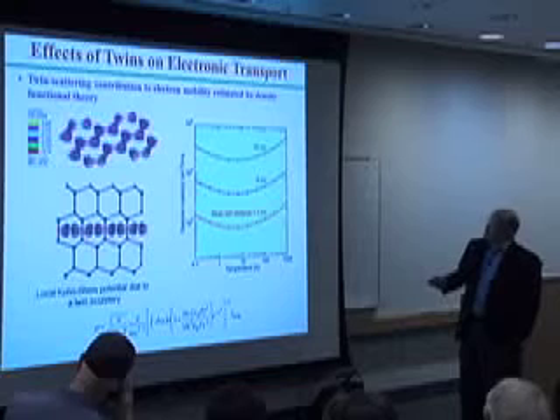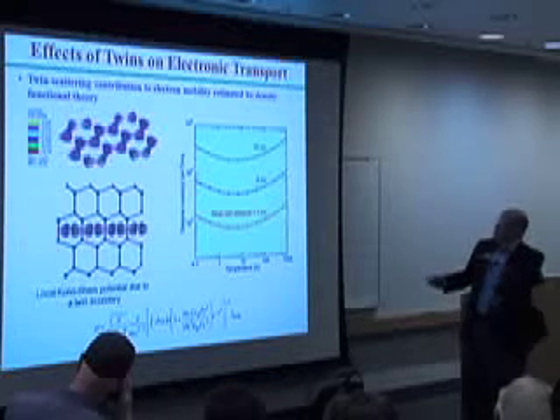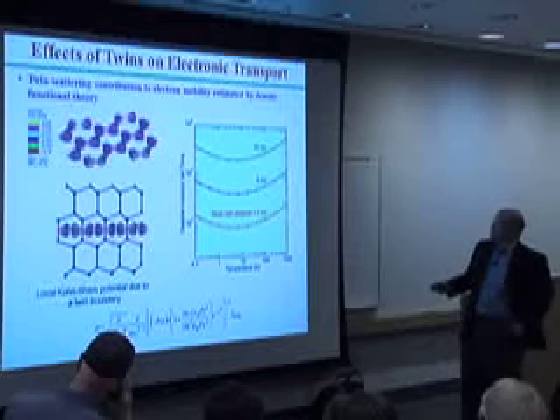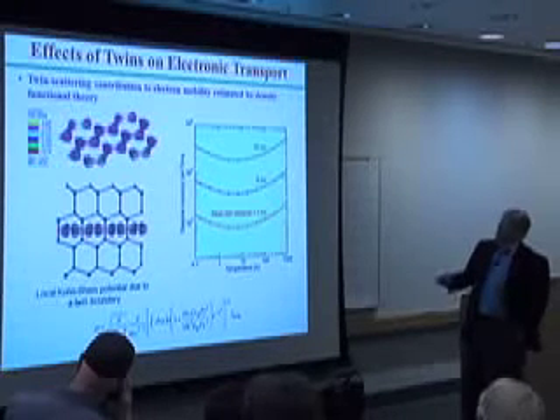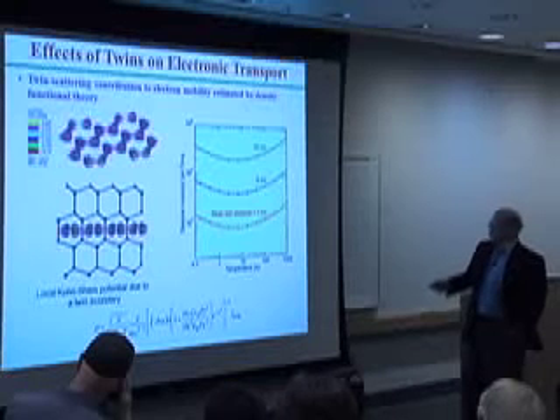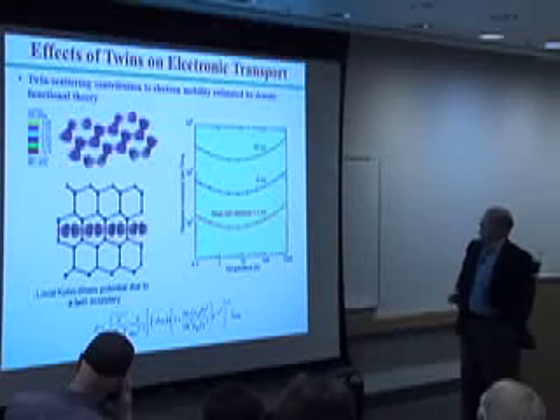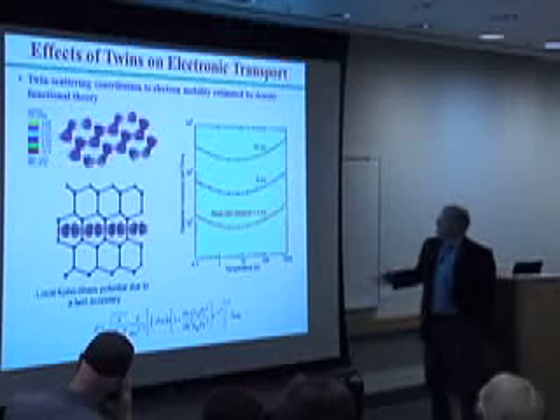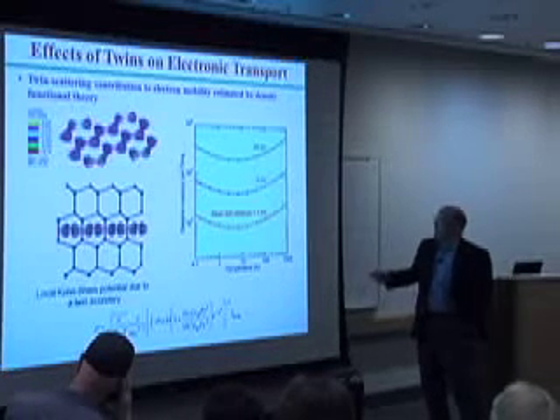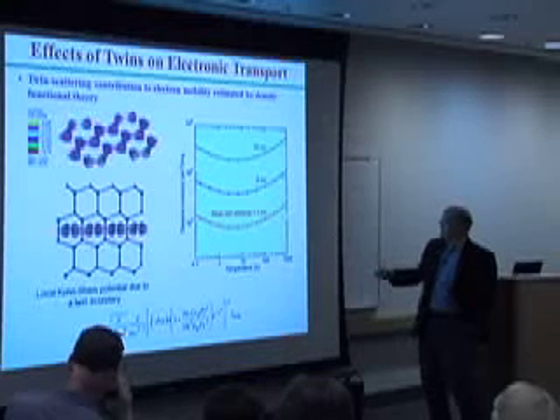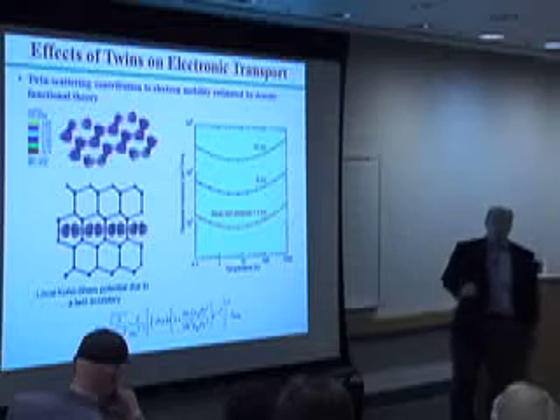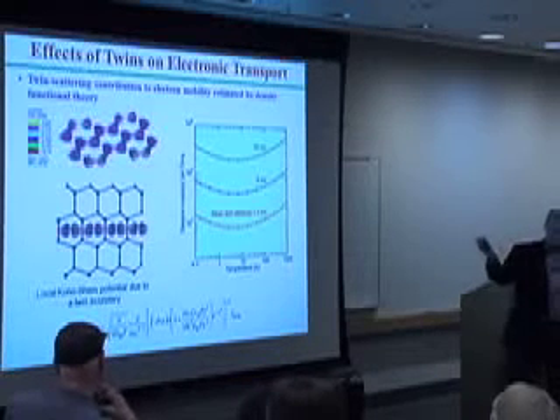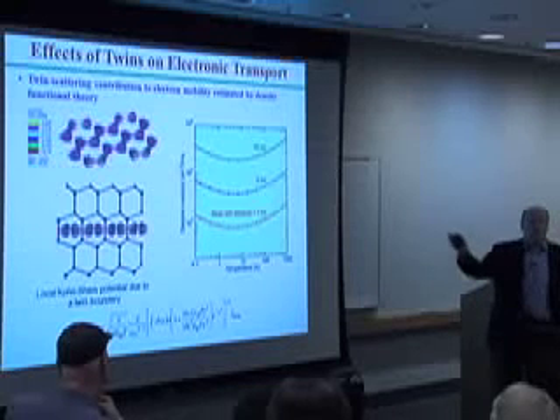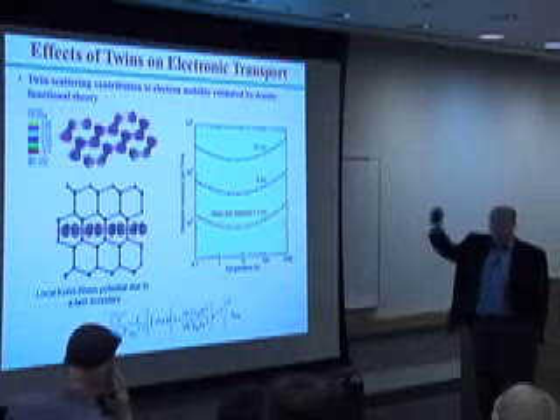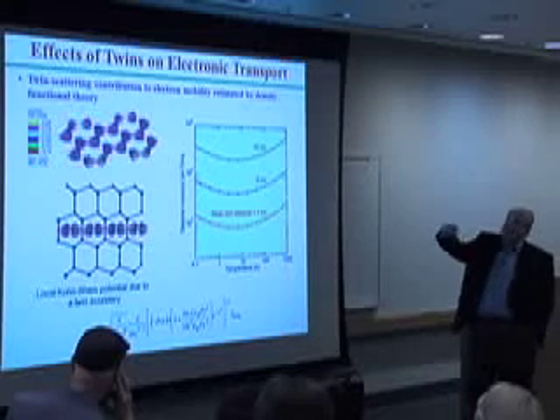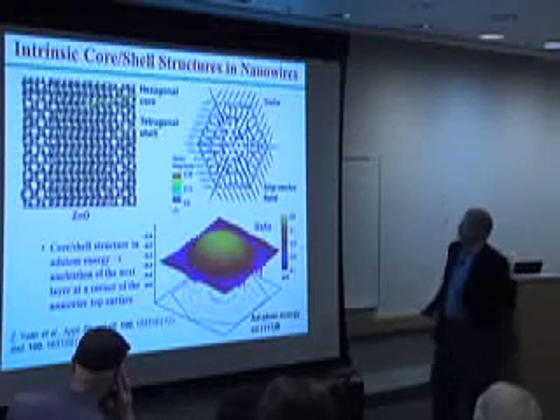What he's discovered is that for the kind of separations between these twins that we observe, which are on the order of a nanometer, the mobility of majority carriers is limited by these twins. That is to say, this mobility is on the order of 1,000, increasing to maybe 2,000 at higher temperature. That's comparable to what you'd see in material that's doped mid-10 to the 17th or thereabout in gallium arsenide. So it's just as effective as impurities in reducing the mobility of the material, and so it's something that we chose to do some work on.